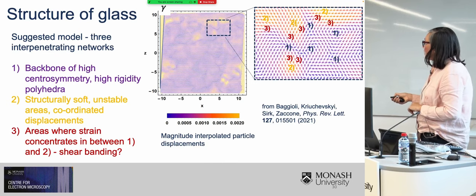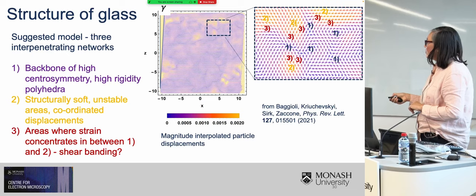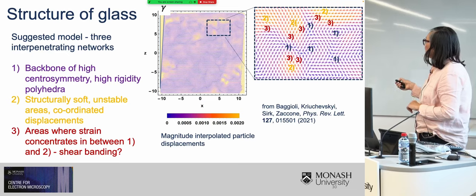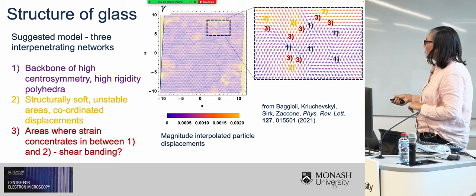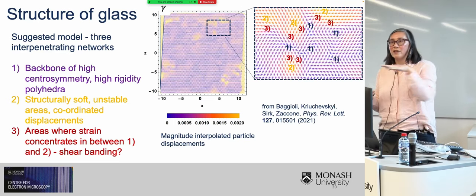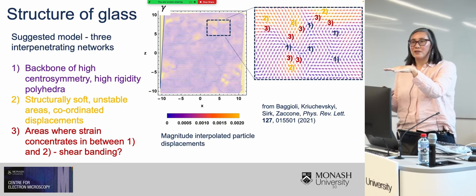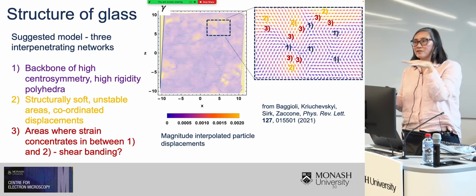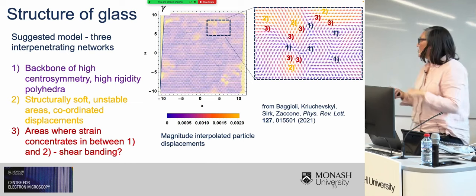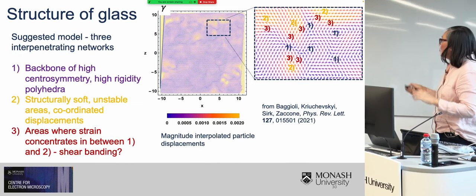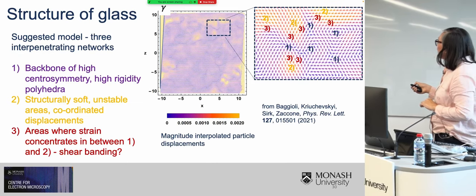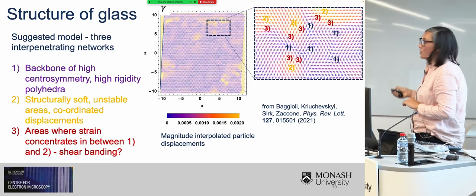So you have this backbone here of high centrosymmetry and high rigidity polyhedra, as you can see from these points here. And then you also have some structurally soft regions that are unstable, and they actually undergo very coordinated displacements. Okay, so the magnitude and the direction of these displacements is all the same. And then in between, you have the area where the strain actually concentrates.